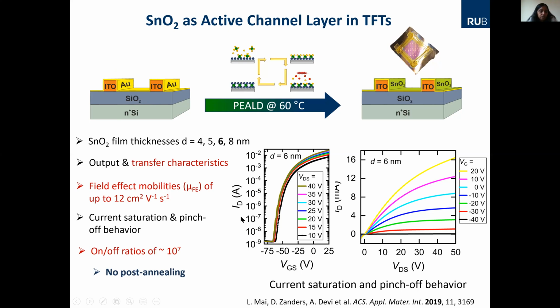We measured the IV curve. So you have the source and drain current with the gate and source voltage here, and then you measure the saturation and the transfer characteristics for films of different thickness. We found that for the film of 6 nanometers, we had optimal electrical characteristics in terms of mobility, which is around 12 centimeters square per volt per second, which is quite impressive when you compare it to the literature values known for ALD grown films.